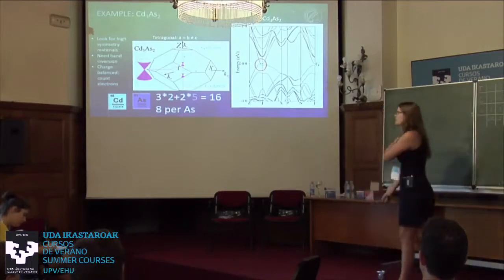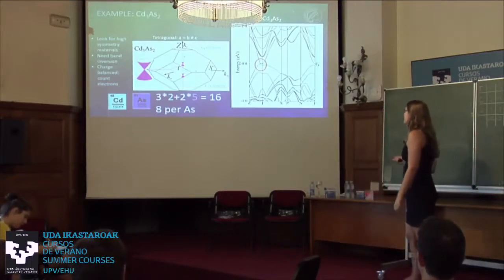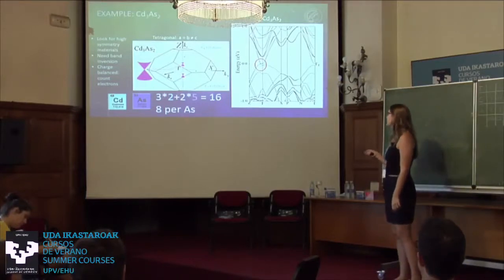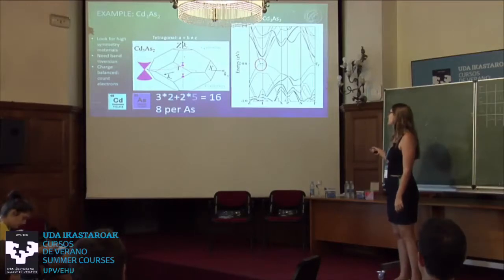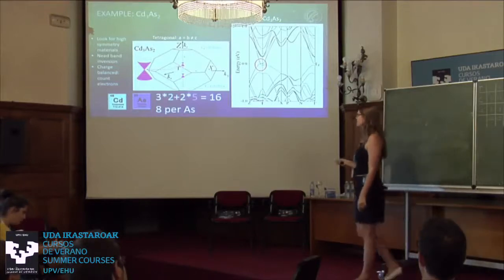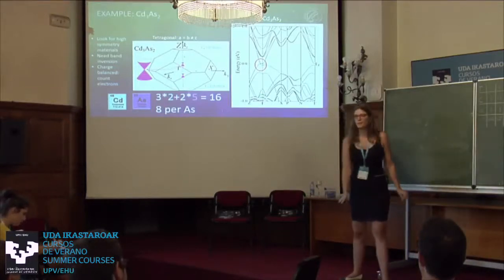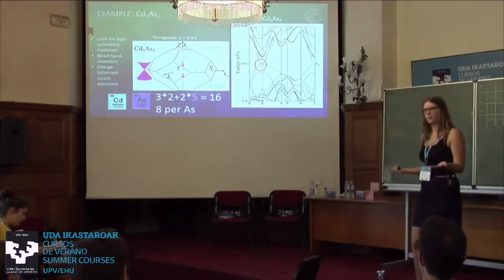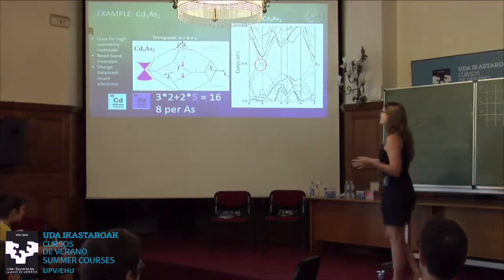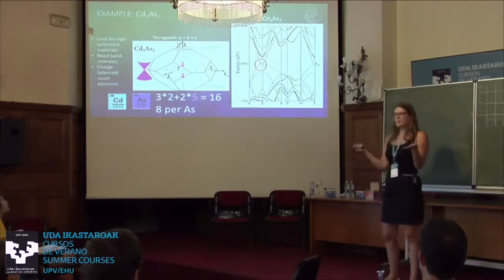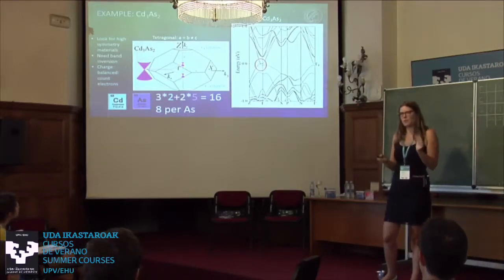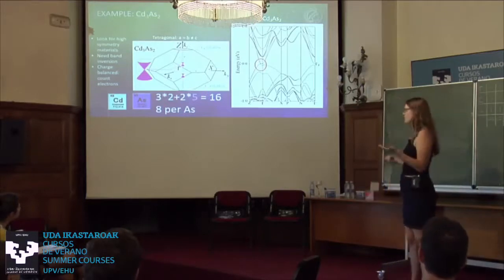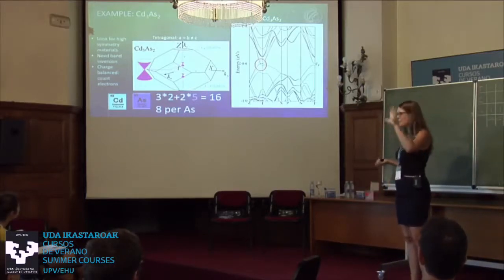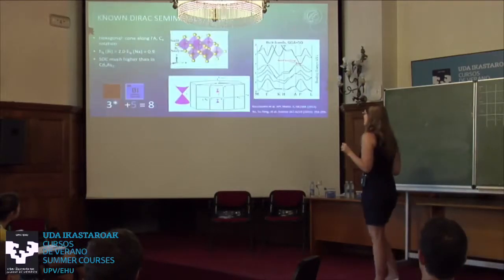So this is cadmium arsenide, the first one discovered. And here you can see the Brillouin zone, and you see that we have the C4 rotation along gamma Z, and this is where the protected crossing is, and along gamma X, this crossing gets gapped. Also, if you count the electrons here, we have 8 per arsenic, so this is a charge balanced compound. And then, if you think about electronegativity difference, that's not that high. Those elements are relatively close together in the periodic table, but they're also not too heavy. Okay, this is still kind of a hand-wavy argument. I will get back to this later.